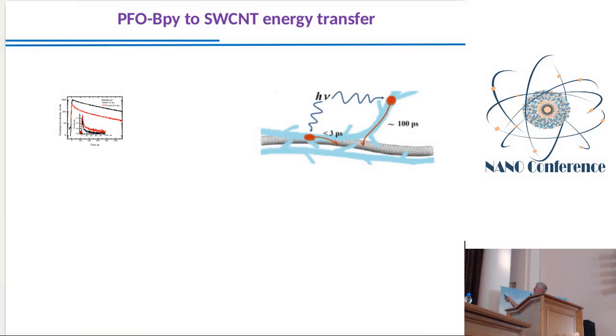Okay, yes. In fact, we didn't try photoluminescence measurement of carbon nanotubes. I have some results here. We tried photoluminescence when we excited the polymer. Here, under excitation of the polymer, we see energy transfer from polymer to carbon nanotubes. Photoluminescence may provide some information, but we also tried transient absorption measurements.